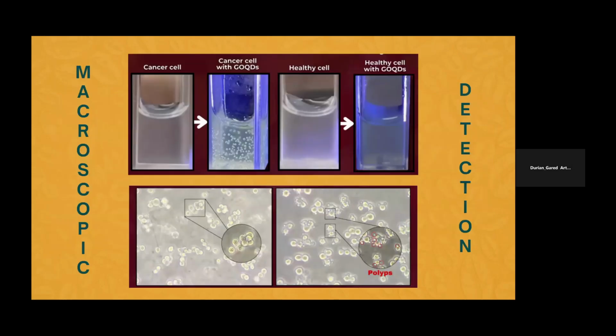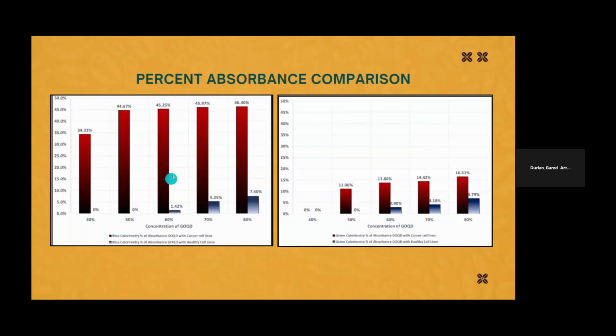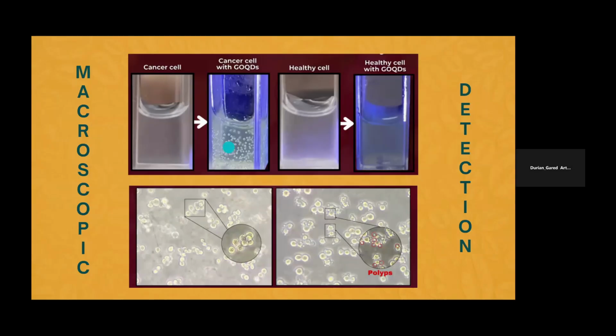Then when we expose HCT116 colon cancer cells and healthy cells to GOQDs, the difference was clear. Cancer cells fluoresce at 46.30% in blue light, while healthy cells only fluoresce at 7.5%. The reason behind this is that GOQDs bind tightly to cancer receptors, reducing self-quenching and making them shine better. Under the microscope, cancer cells treated with GOQDs form visible bubbles and changes that healthy cells did not show. Therefore, it is a selective binding, and the binding prevents quenching, which amplifies the fluorescence and allows cancer to be detected with the naked eye.